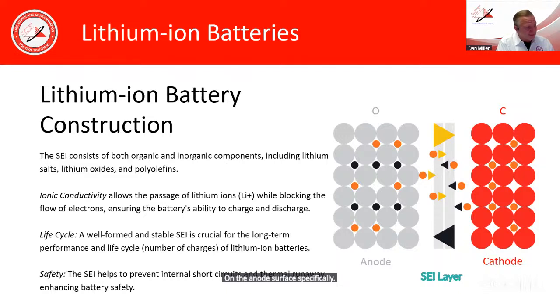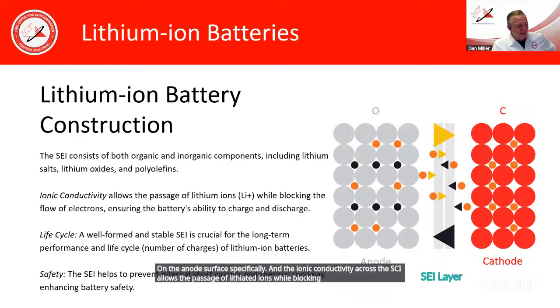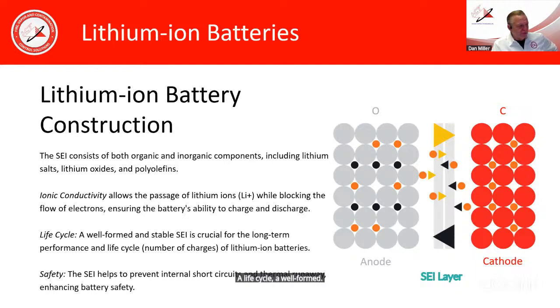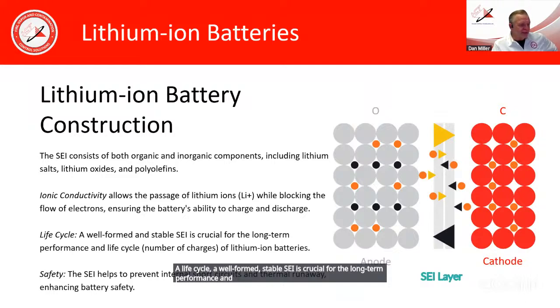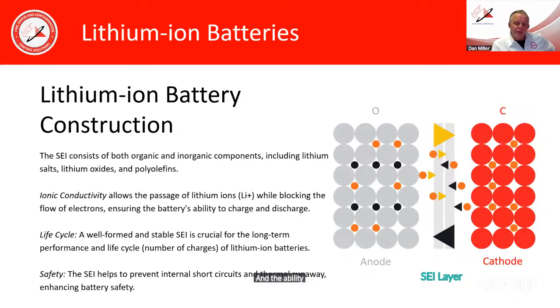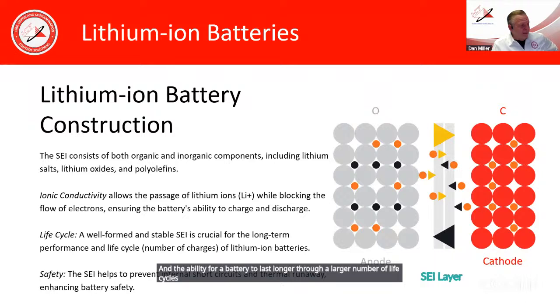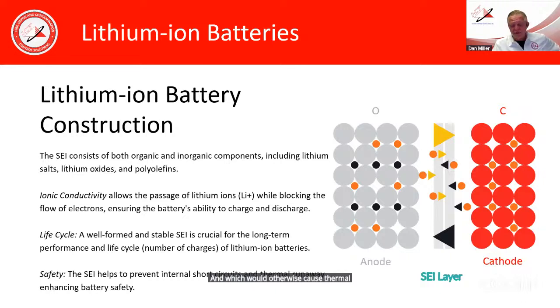The ionic conductivity across the SEI allows the passage of lithiated ions while blocking the flow of electrons, ensuring the battery's ability to charge and discharge. A well-formed, stable SEI is crucial for the long-term performance and life cycle, or number of charges, of a lithium-ion battery. As engineering and technology has moved forward, the SEI layers have become better over time, and the ability for a battery to last longer through a larger number of life cycles is the result. The SEI also helps to prevent internal short circuits between the anode and the cathode, which would otherwise cause thermal runaway inside of the battery. So a good SEI layer enhances the battery safety as well.